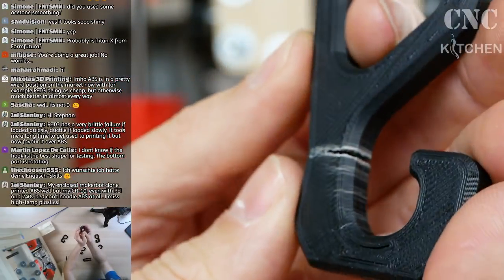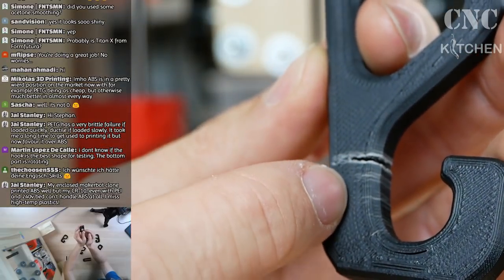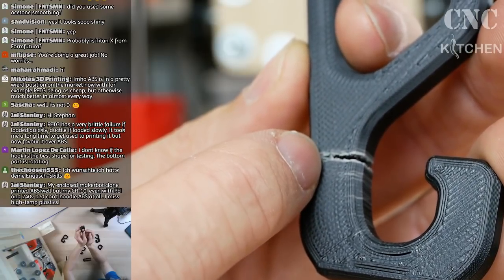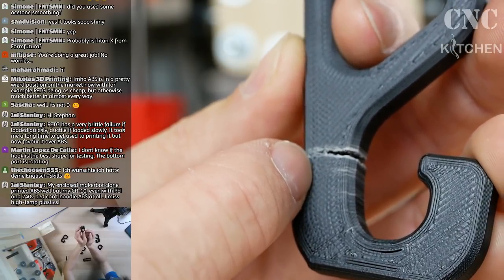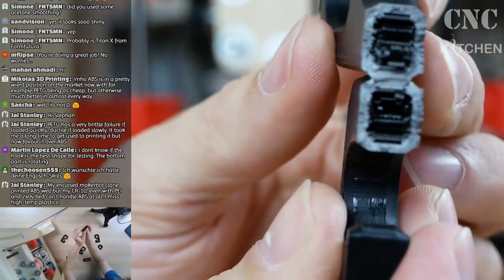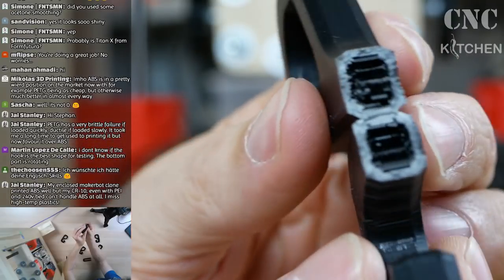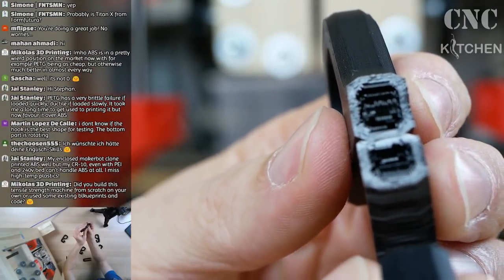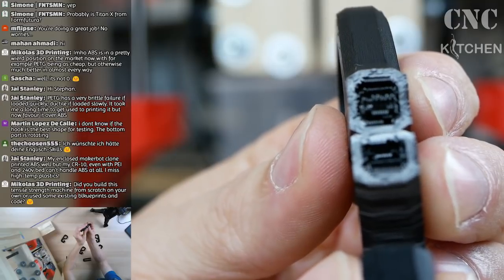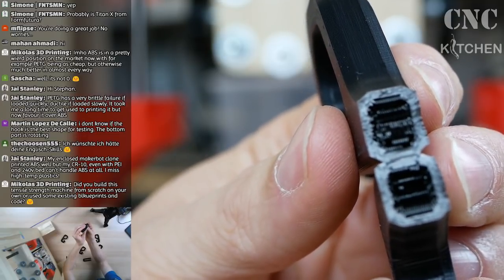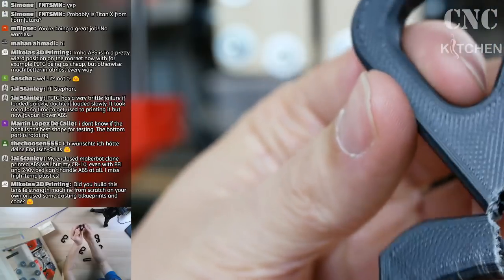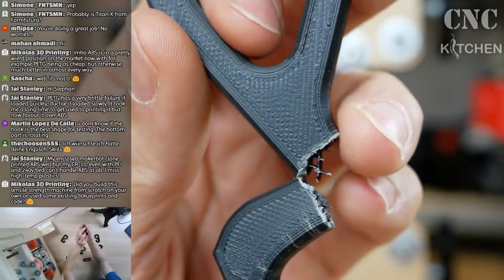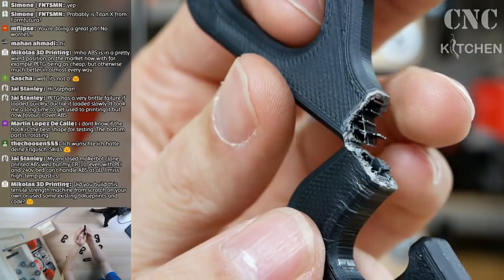There we go. So we see where it failed, and you can nicely see the white lines right here, which start to form at the point when the material is starting to yield. If I break this open all the way, you can see how it looks from the inside. So I didn't print these specimens with 100% infill. That's actually not what I want to have, because this shall be a good representation of the settings you usually use if you print a part.